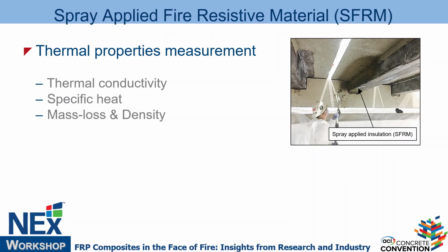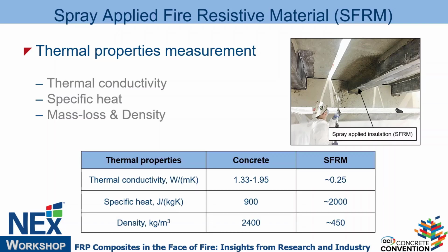So, can I model this thing? Yes. If you do ASTM standard tests on that fireproofing material to determine thermal conductivity, specific heat, mass loss, density, then you can go to any software, add an additional layer, assign it these properties, apply ASTM E119, and you can still calculate the temperature of the steel, which will improve with the fire protection.